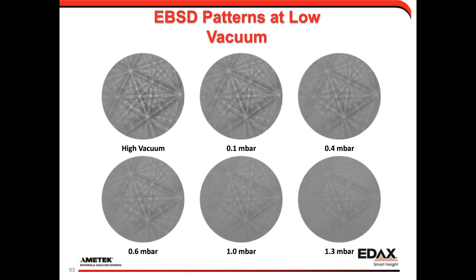Now, another alternative to coating that's becoming more and more available to people is using the low vacuum capability of SEMs. And so by introducing a little bit of pressure into the chamber, this can help dissipate the charge on the surface as well. So this just shows the effect on EBSD pattern quality by increasing the chamber pressure from 0.1 millibar up to 1.3, where now the gas molecules in the chamber are disrupting the signal towards the phosphor screen as we put more of them in there.